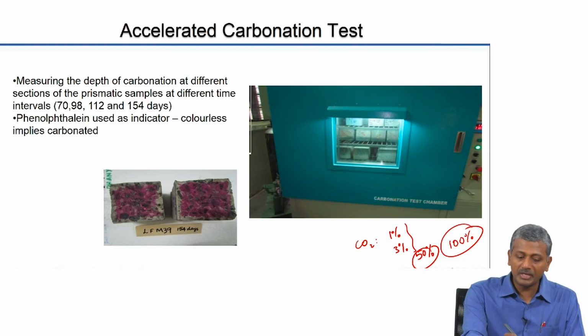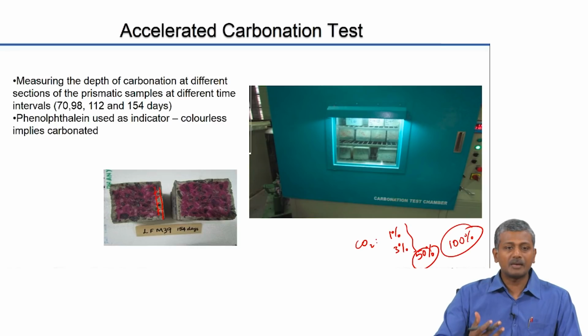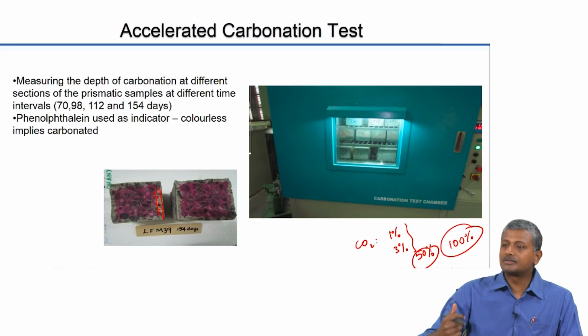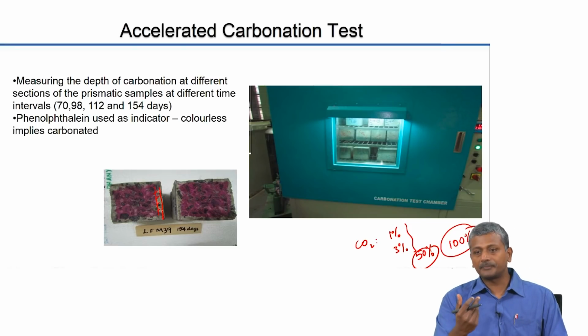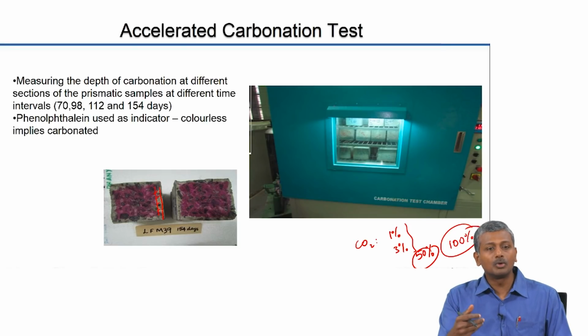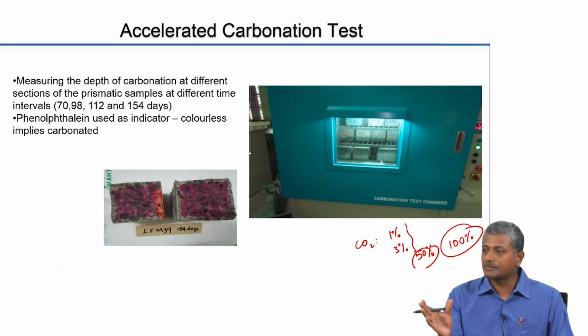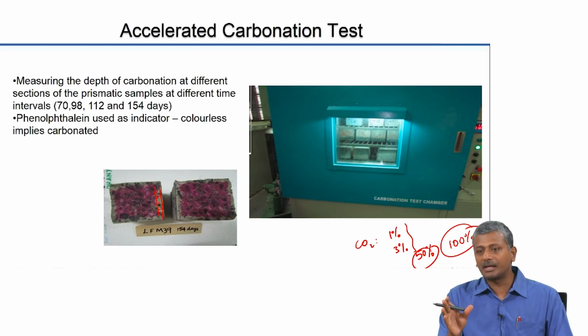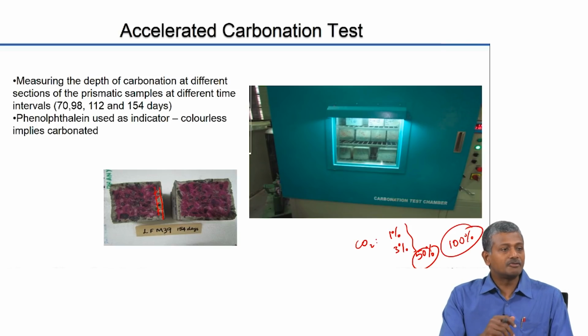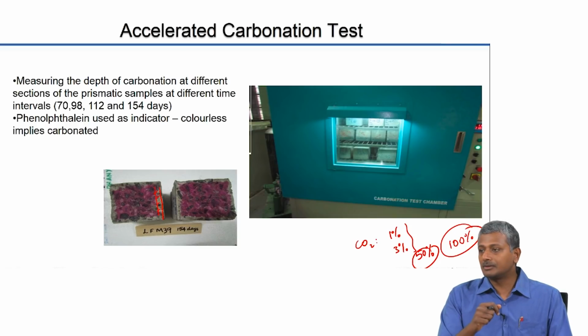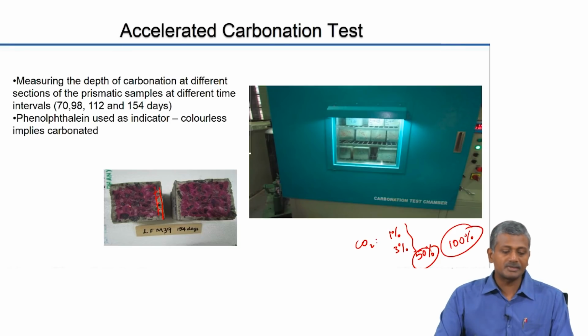So, beyond a certain pH, you'll start seeing a colorless band on the surface of the concrete. When carbonation happens, CO2 penetrates the concrete and interacts with the calcium bearing species in the concrete, which leads the concrete to become more and more acidic. So, the pH keeps reducing. When the pH crosses about 11.5 or 11, or sometimes even less than that, about 10.5, the phenolphthalein would indicate a colorless concrete. For all pH levels above that, it will indicate a pink concrete. So, concrete inside is obviously not carbonated, concrete at the surface is carbonated in this case.